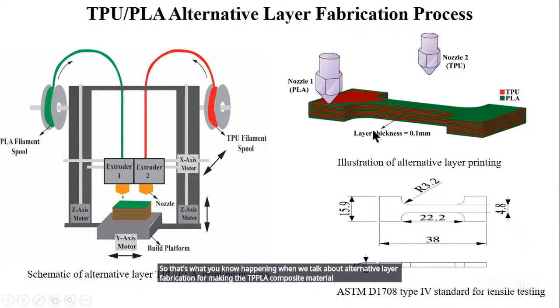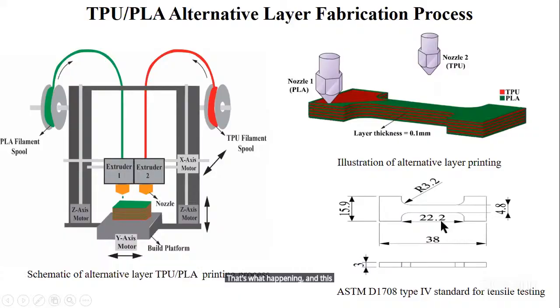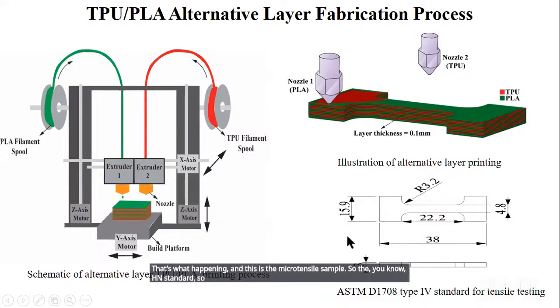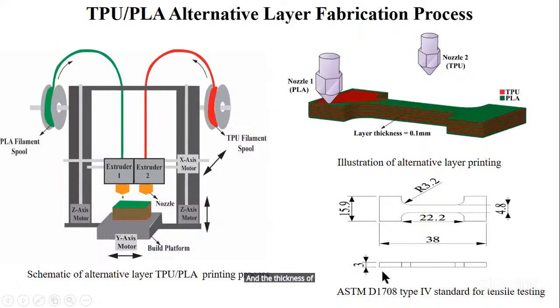All right, you can see the schematic again. One nozzle is printing the green color PLA, and the second nozzle is idle. Once it is done, the second nozzle will come and print the TPU. That's what is happening. And this is the micro tensile sample, per the ASTM standard: 38 overall length, 15.9 width, 4.8 gauge width, gauge length 22.2, and thickness of 3 millimeters. That's the dimension we have printed.